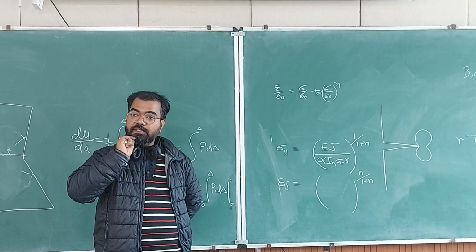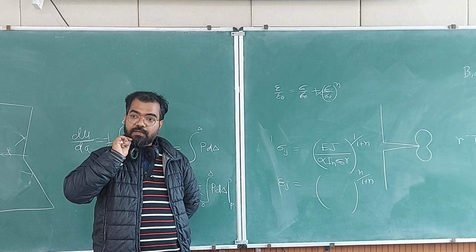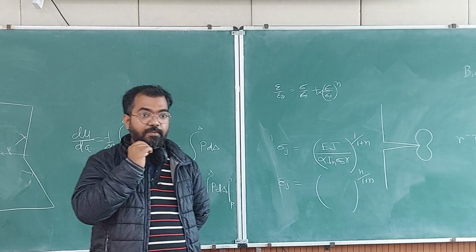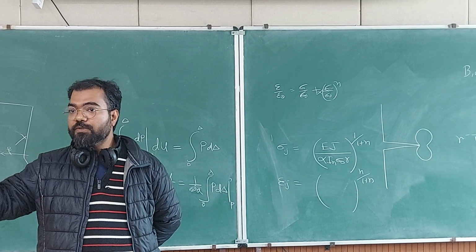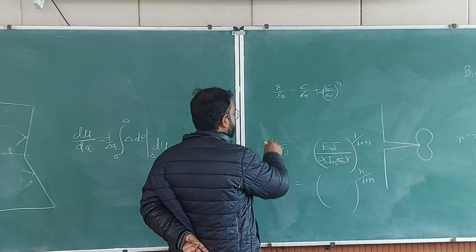But we did not have this kind of representation of stress strain in the case of George Irwin, right? Because that was only valid for elastic theory. This is coming from the Ramberg-Osgood representation of the elastic plastic stress strain curve. Okay, so this was done by